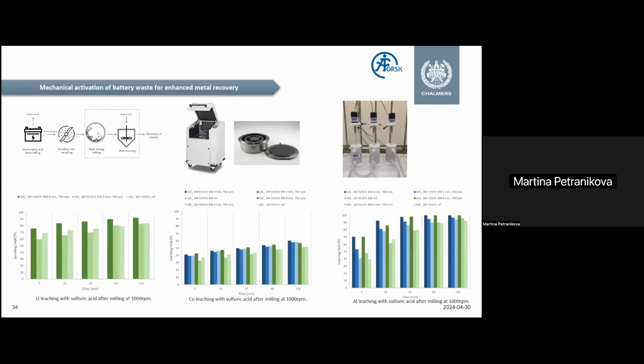What we have also been working on is mechanical activation of the black mass, because as we all know, there is also binder or glue, which is used for the cathode materials on the aluminum foils. And this glue can also affect the separation and the contact of the leaching media with the material. So we have tested mechanical activation with high energy milling.